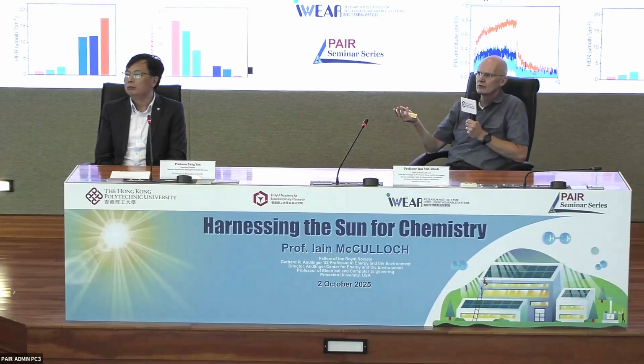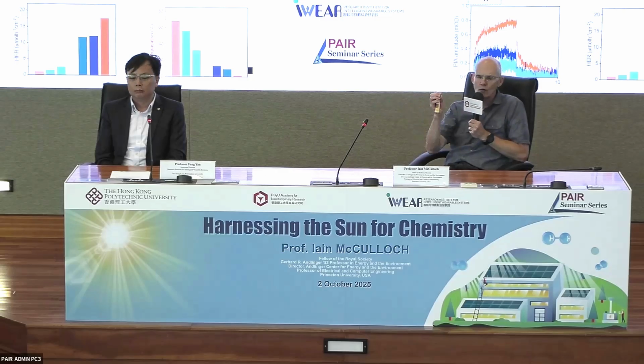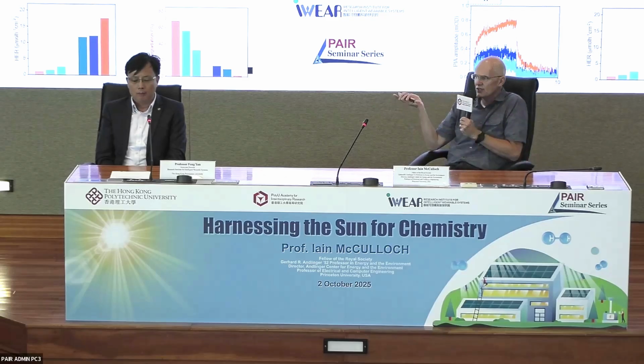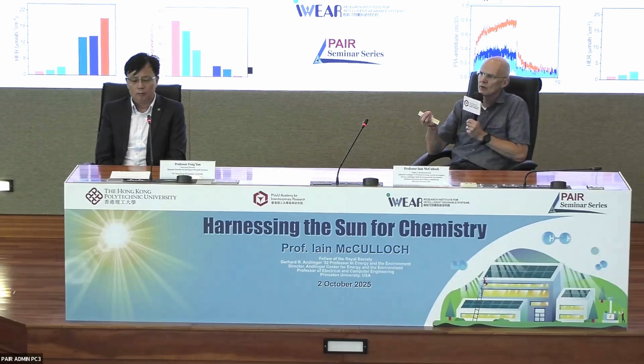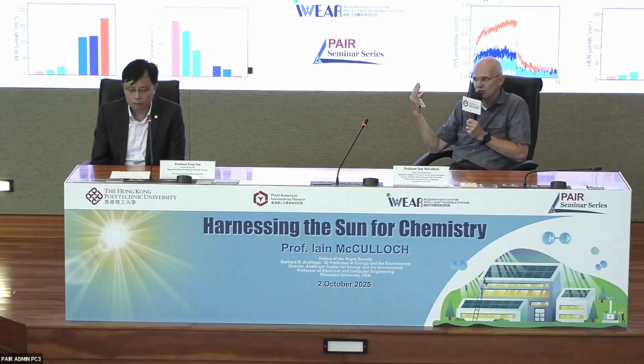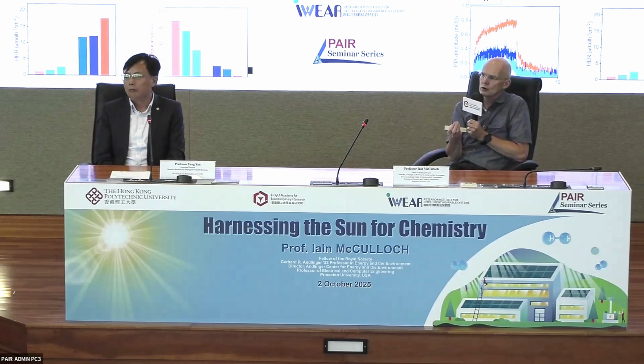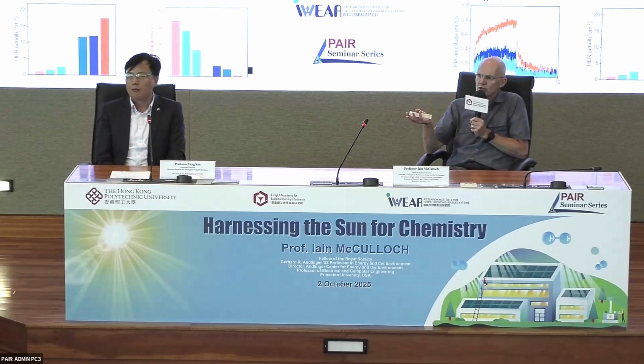It's like everything else. If you look at perovskite research 10 years ago, it was a mess, right? But slowly we started to see that maybe the interface is a problem, maybe we should replace formamidinium with cesium. All these little iterative improvements go on over time. This technology is pretty new. I think the key to commercial success will be to find a sweet spot in application versus stability. It's not going to give you 30-year lifetimes. Organic solar is not going to do that for you either. And the charge densities here are much higher than in a solar cell, so the opportunity for chemistry is also much higher, which can be good and bad. So we probably need to improve the stability dramatically, but then we probably have to find short-lifetime applications, just like in solar, the disposable type of application.